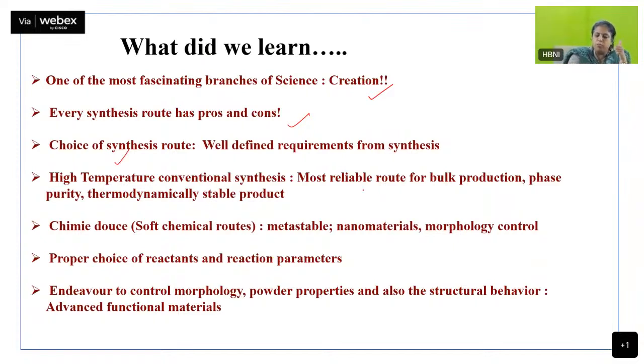If you want the most reliable route for bulk production, phase purity, and a thermodynamically stable product that doesn't change phase during application, go for the high temperature route. Chimie douce, which is a name for soft chemical routes, can give you metastable phases, can give you nanomaterials. You can have morphology control, you can make nanorods, nanotubes, whatever you want. Depending on what you want, you have to choose the best possible soft chemical route for you. You have to have proper reactants and reaction parameters.